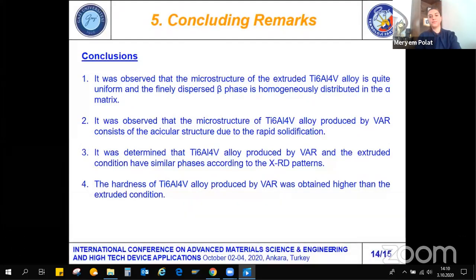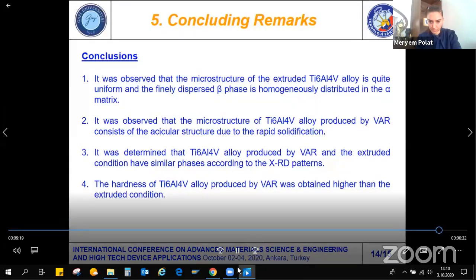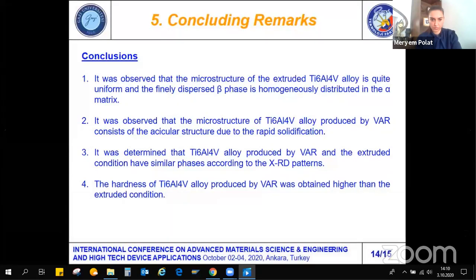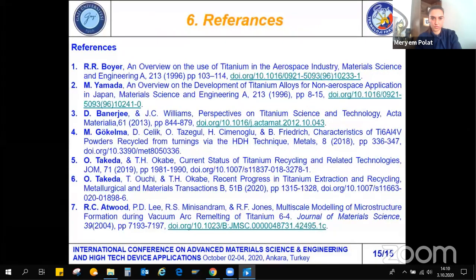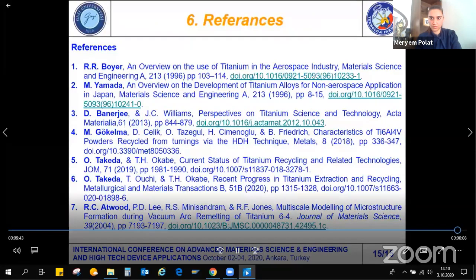It was determined that the titanium 6 aluminum 4 vanadium alloy produced by vacuum arc remelting and in extruded condition have similar phases according to the XRD patterns. The hardness of titanium 6 aluminum 4 vanadium alloy produced by vacuum arc remelting was obtained higher than the extruded condition. Here you are seeing my references.